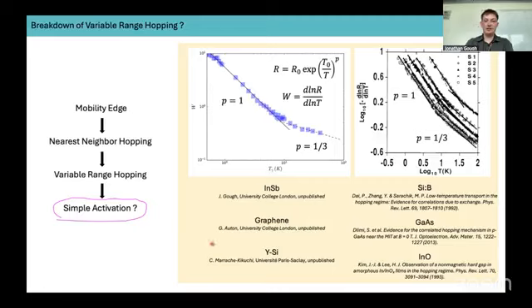It's also been observed in graphene by my colleague at UCL. There's also results in yttrium silicon, a superconducting material, and there's also published results, for example, silicon boron here, gallium arsenide, and a very famous result in indium oxide, again, another superconducting thin film. You can see this very similar behavior where they observe p equals a third, and then some critical temperature, and then p equals 1, indicating this transition to this low temperature activated regime and this breakdown in variable range hopping.